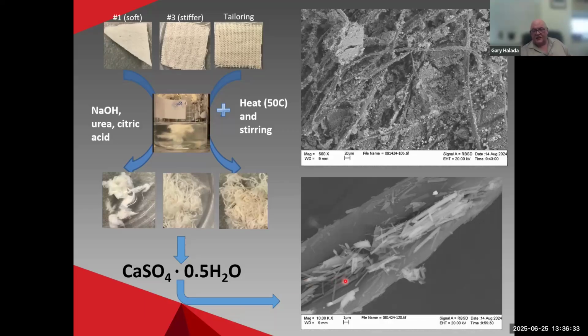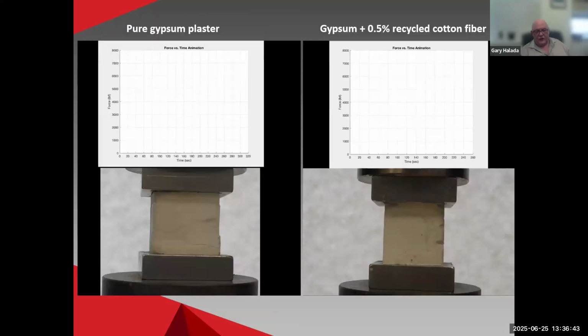And you can see here at the top picture, from an electron microscope image I took, that the fibers are indeed adhering to a lot of the crystalline material, and this makes it a bit stronger. We did some compression testing. See if I can make it work.